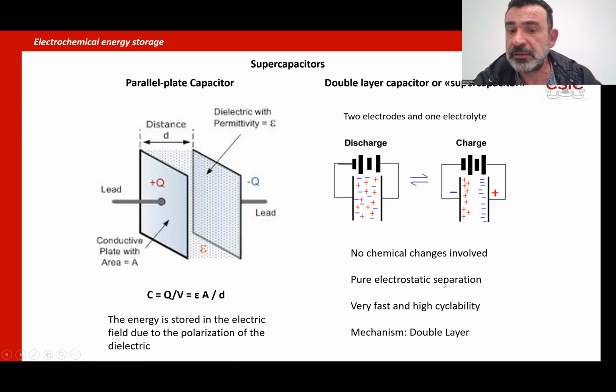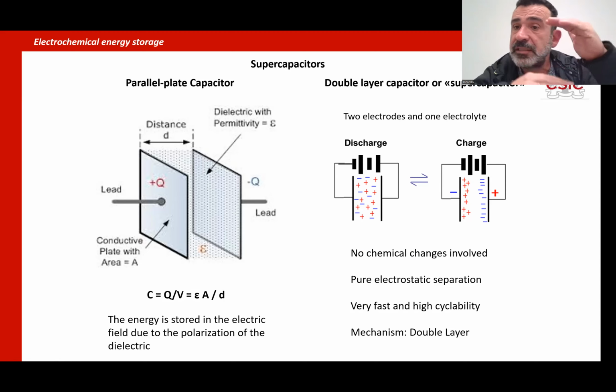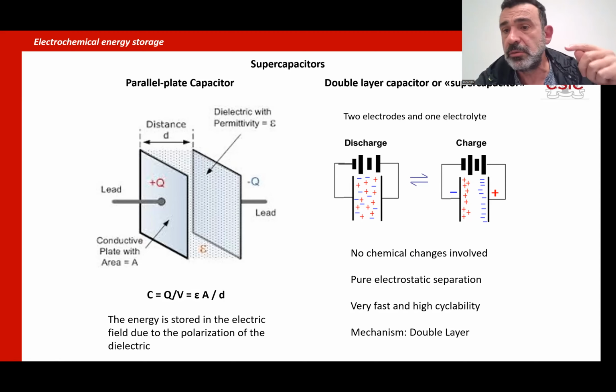It's just pure electrostatic separation. This is the reason that the processes are very fast, and this is the reason for the high cyclability. You can charge and discharge 1 million times and nothing happens. You are not modifying the chemical structure of the electrodes. Remember, in lithium-ion batteries, you are changing the structure when lithium goes into the material.